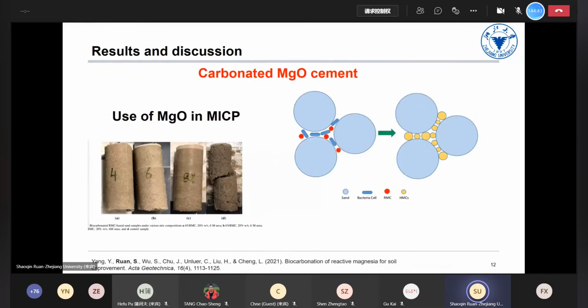And previous speakers also mentioned MICP. MICP is also quite a popular research direction in this area. It uses bacteria and some calcium-bearing salts, like calcium chloride. Previously, we also conducted some research regarding the use of MgO in MICP. We introduced reactive magnesium cement and bacteria to produce hydrated magnesium carbonates to solidify these sands. The results are quite good, and I think it is a very promising field.